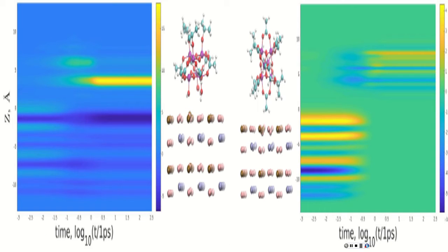So again, there is a comparison of two structures, one with hydroxyl, another with acetic, part of the cluster facing the perovskite. So Landon did practice these almost standard protocols for non-adiabatic dynamics facilitated by nuclear motion, and computed the dynamics of charge distribution on the cover as a function of position, y-axis, and time, x-axis.